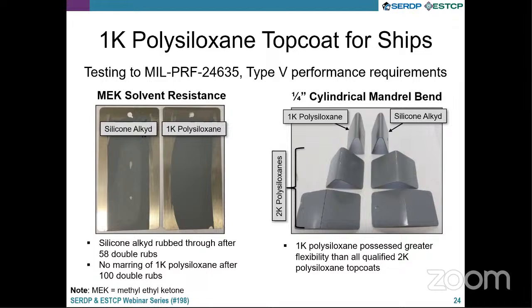At the same time, if you perform a quarter-inch cylindrical mandrel bend, you can see that the single component polysiloxane can easily bend, the polymers can stretch, and there's no cracking whatsoever on that sample, similar to the silicone alkyd. However, when we take the qualified two-component polysiloxanes, which possess a much higher cross-link density, you can see that after even bending them slightly, they all crack.